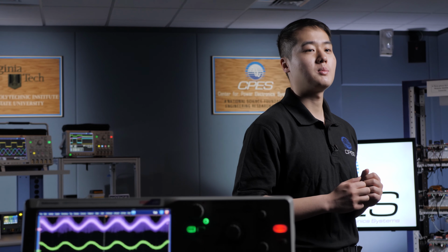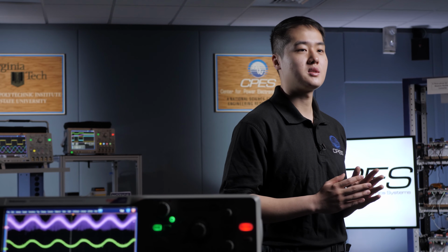My presentation topic today is high surge current capability in ultra-wide bandgap gallium oxide power rectifiers through device package co-optimization. We studied the surge current capability of gallium oxide power rectifiers, and we found that the double-side cooled gallium oxide Schottky barrier diodes with a 3 x 3 mm square Schottky contact area can sustain a peak surge current over 60 amp, with a ratio between the peak surge current and the rated current superior to that of similarly rated commercial silicon carbide Schottky barrier diodes.